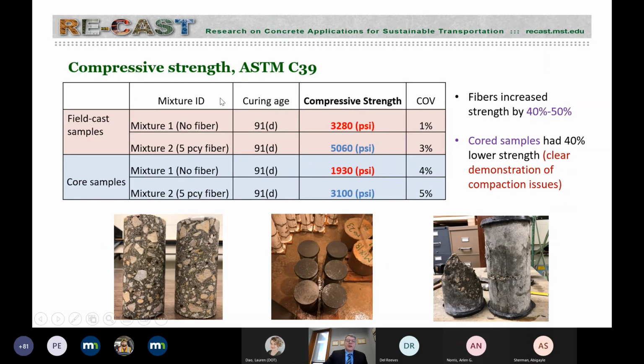So starting with the compressive strengths, reported here at 91 days. The samples were always maintained moist cured, even when we brought them back to the lab. And you see that the field cast samples' coefficients of variation are very, very low. This is really impressive. I showed you the energy of consolidation, how intensive it is, yet we get very good consistency in terms of testing. These are averages of 3 samples.